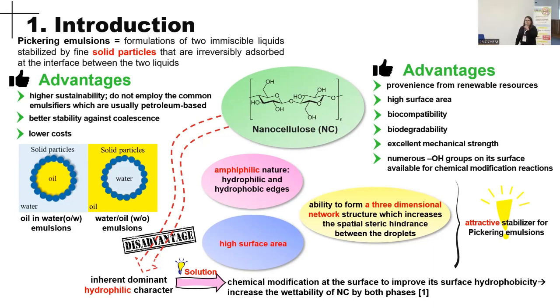However, what really sustains the use of nanocellulose as stabilizers for Pickering emulsions is in fact its amphiphilic nature, since many authors claim that the cellulose crystals present both hydrophobic and hydrophilic edge bands. And also nanocellulose has the capacity to form a 3-dimensional entangled network when it's dispersed in water, and this network can increase the steric hindrances between the droplets from the emulsion and increase the stability of the emulsion.